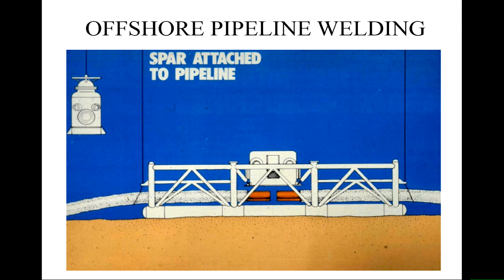Here is an example where you actually just set the welding procedure up on the seabed. So we have this spar attachment system here. This is the weld that you've got to make. Might be that you had to cut a section out to do that. This is sitting on the seabed. Everything's lined up there, and then you lift the whole thing out of the water to be able to do the repair. You might have a system where you have a pressure chamber loaded over the top here, but in some cases you can't achieve that, and you might want to lift just to check what's going on. But this is the normal sort of arrangement. You have this spar system which is loaded, you line up everything, and then if you're going to put your pressure chamber, you can put that down over the top.